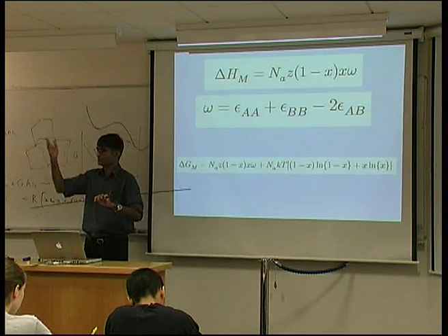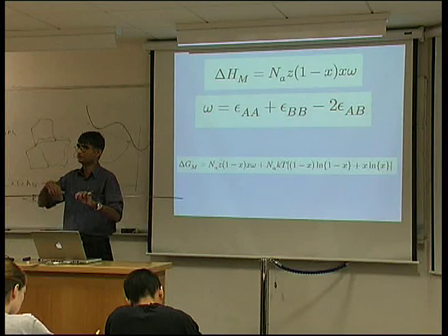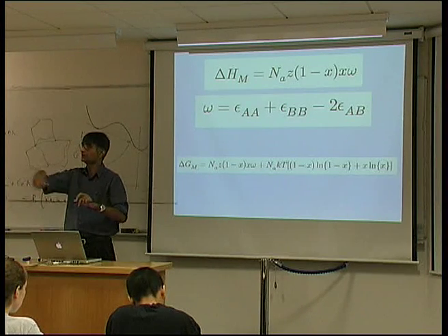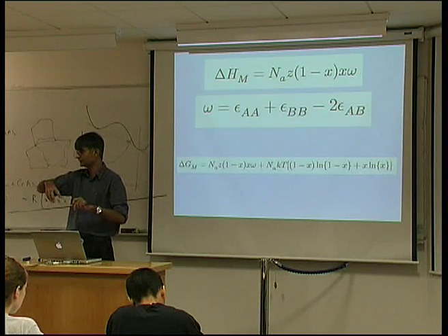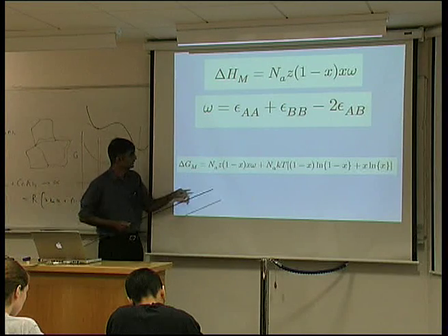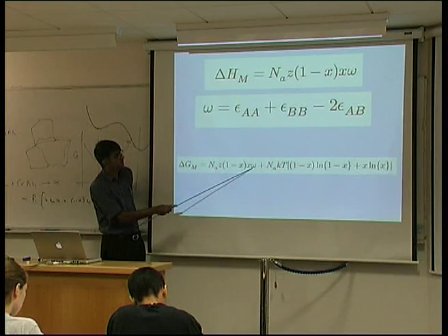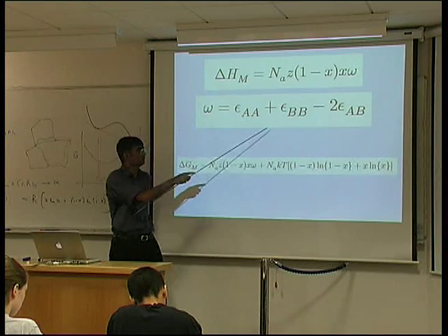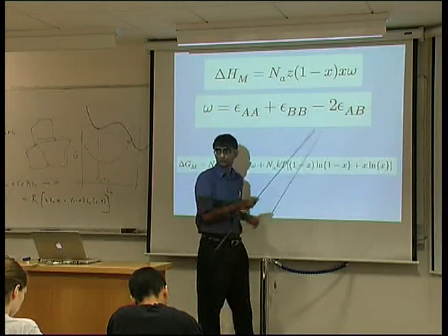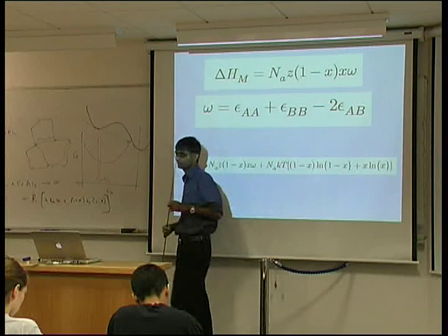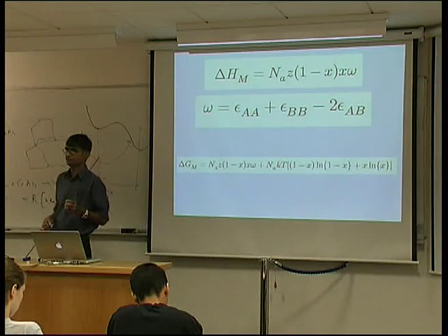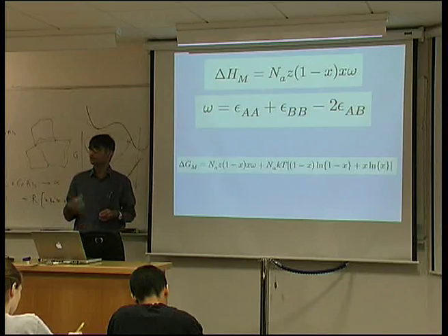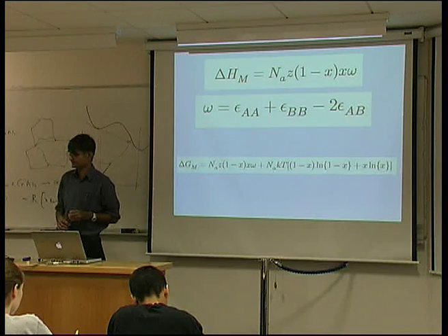Z is a coordination number, because the number of bonds that you form depends on how many atoms you have surrounding a particular atom. And omega here is simply the change in binding energy when I take an AA bond and a BB bond, and form two AB bonds from that. So that's the equation for the free energy of mixing. If I differentiate that with respect to x,